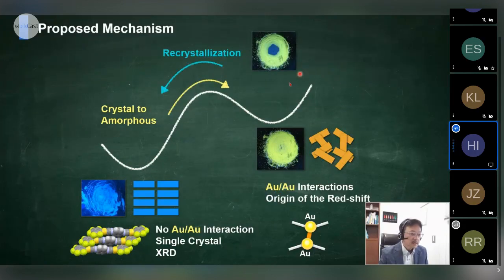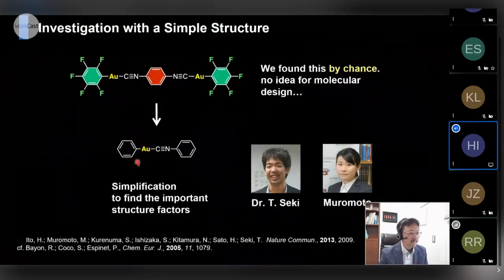And the amorphous state would be more thermodynamically unstable compared to the crystalline state. So when we add some solvent, this solvent can induce recrystallization to the more thermodynamically stable crystalline state.